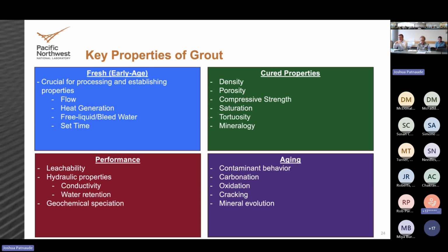The information that gives us on the grout side of things is it shows us if some of the retention mechanisms that we've engineered into our material still give lower release in a TCLP test. That gives us high confidence that in our realistic disposal environment, which is usually neutral to alkaline, things are going to perform well, because we went very extreme, where we'll never see high acid, and things still perform well.